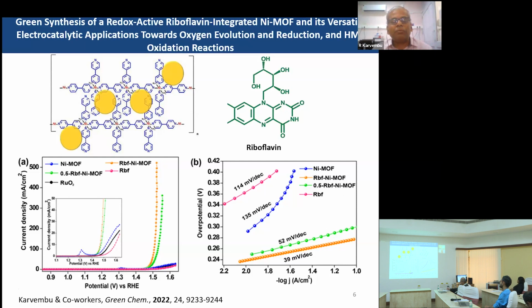Initially we modified the nickel MOF with the help of riboflavin without affecting the original crystal structure of the MOF, and this has been used as an electrocatalyst for oxygen reduction and oxygen evolution reactions, and this catalyst has also been used in some biomass conversions like conversion of HMF into FDCA.